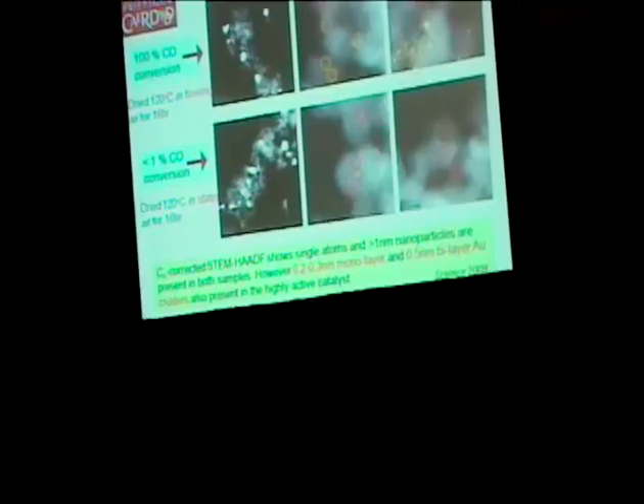So following this, we took the very active catalyst and we exposed it to heat treatments to try and sinter the gold particles to see what effect this had on the activity and also what effect this had on the particle size distribution.